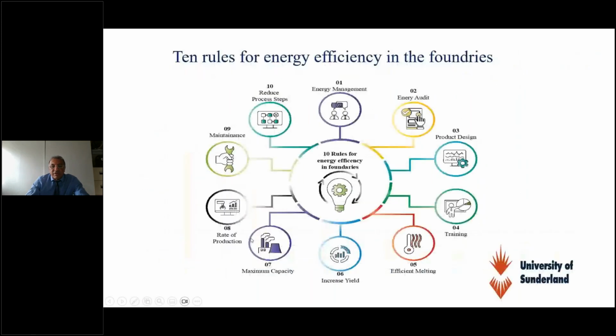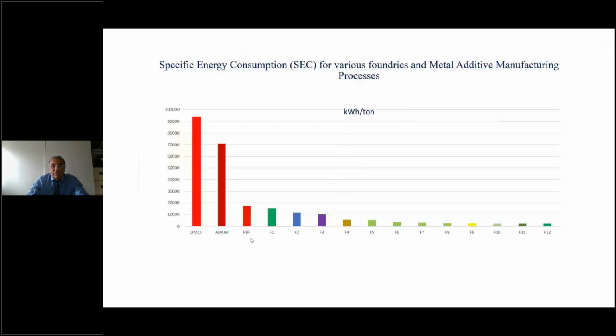So in comparison with energy consumption of PBF, powder bed fusion, ADAM that I told you is a Atomic Diffusion Additive Manufacturing printing of metal at room temperature, then we sinter it, and DED, direct energy deposition modeling, you can see how much energy per part, per kilogram they consume. We're talking about something like 95,000 kilowatt per ton for DED, ADAM 70,000, and PBF around 18,000, much more than F1, which is the worst case scenario in sand casting foundries.